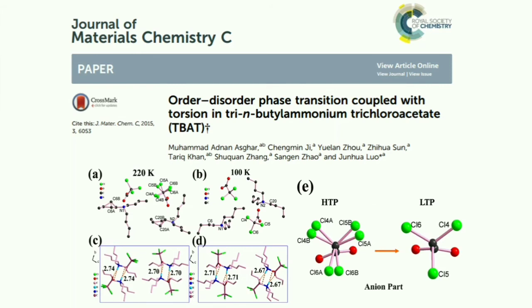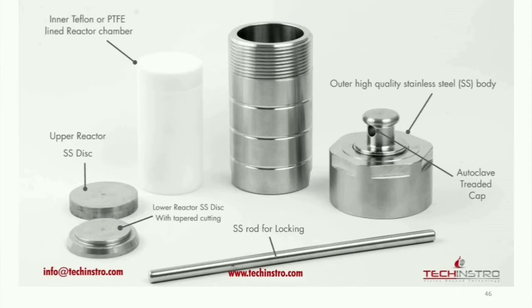In this hydrothermal method, the authors synthesized this compound by mixing tributyl amine with trichloroacetic acid. They mixed both of the reactants in a beaker and then heated the beaker for 3 hours at about 50 degrees Celsius with constant stirring. After getting a homogeneous and transparent solution of these two reactants, tri-N-butyl amine as well as trichloroacetic acid, the mixture was transferred to the Teflon-lined autoclave, which is shown here.